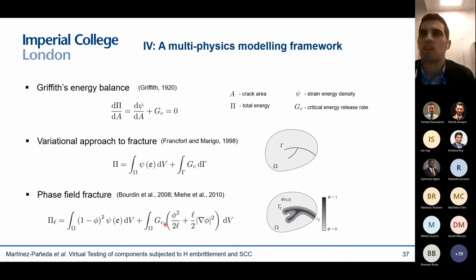So the phase field paradigm, in a way, is a little bit like a damage variable, right? It goes from 0 in the solid, in uncracked material points, to 1 in fully cracked material points, so inside of the crack. And you can see that this surface integral becomes a volume integral, and it's a non-local model, which means that our predictions are mesh independent as long as you resolve this length scale. And then you can also see that it degrades the stiffness of the solid as continuum damage models.